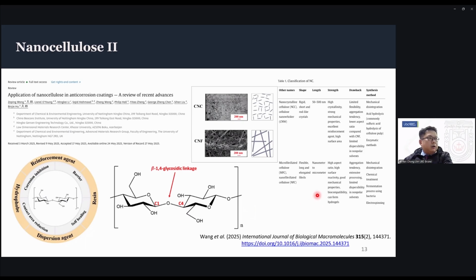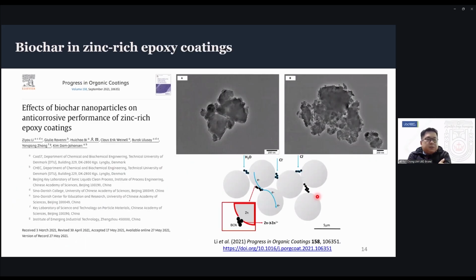More recently, we begin to see the use of biochar reported inside organic coatings. Here is an example, one of the first I've seen, on the use of biochar in zinc-rich epoxy coatings for corrosion protection on mild steel. This was done by researchers in collaboration from the Academy of Sciences, as well as one of the leading coating laboratories in the world, in Denmark, the Technical University of Denmark.